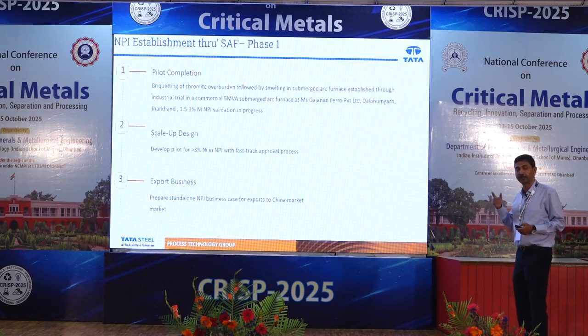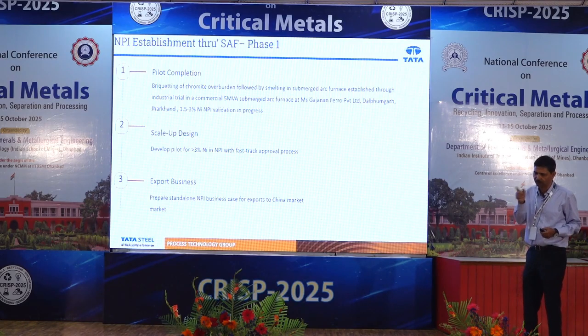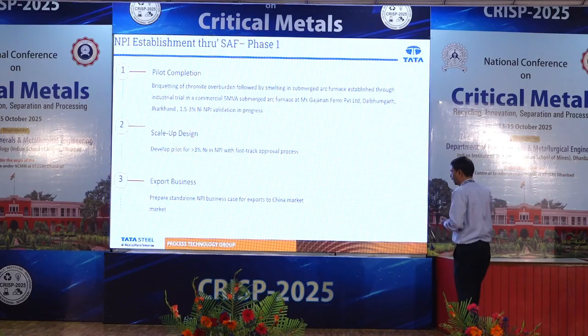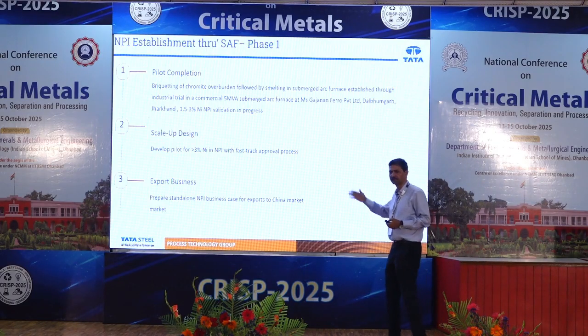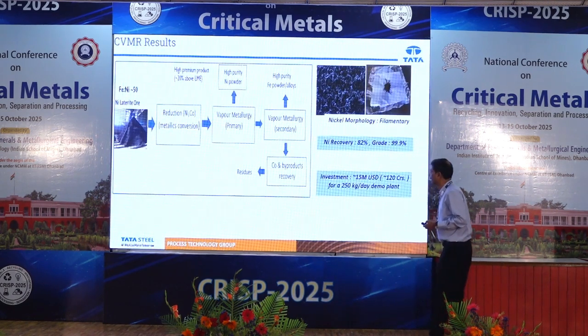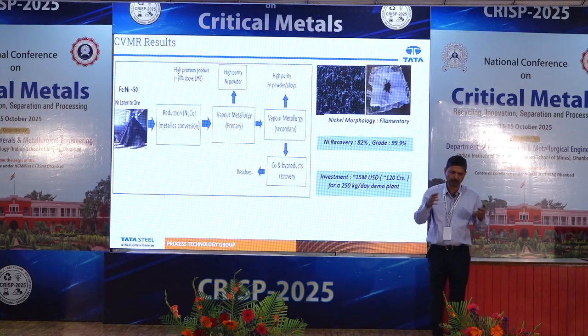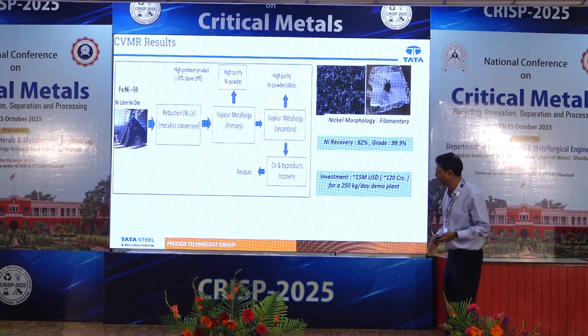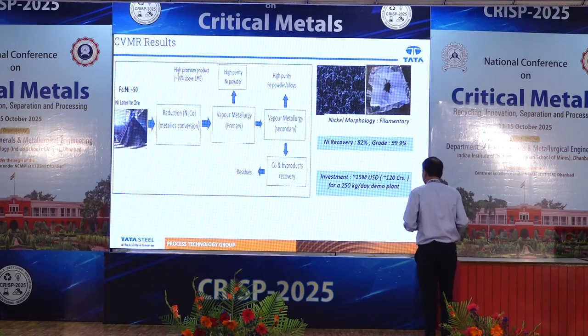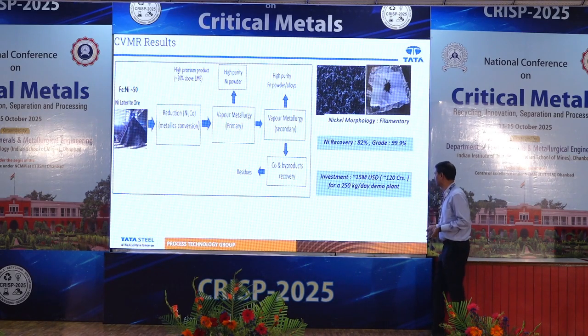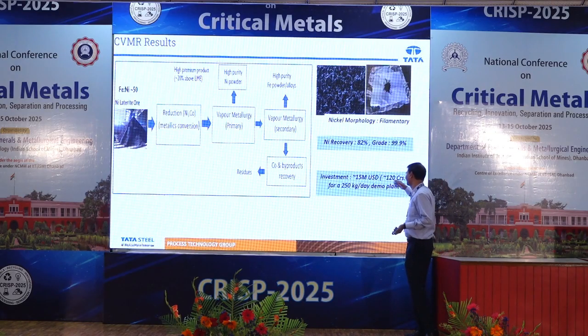Still we are looking, is there any better way to increase the concentration? So with slag modification, taking more FeO to the slag so that the nickel to Fe ratio can be changed. This is the CVMR process. This process also we have tried. The same American company worked with us. Again, they said yes, 82% nickel recovery with 99% everything is possible. But only to put up a 250 kg demonstration plant, they are looking for 120 crores.